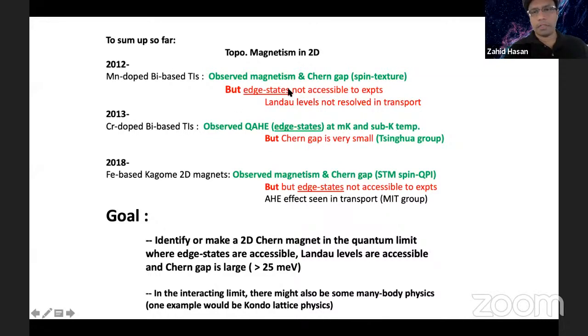In the first material where we observed a Chern gap, this manganese-doped bismuth-based TI, and then in chromium-doped bismuth-based TIs, groups in China, the Xue group, found this quantum anomalous Hall effect, but it's at very low temperature, tens of millikelvin. The gap is small and you cannot really do spectroscopy or a detailed study of this state or what type of magnetism has been realized there. You just do transport, you see quantization, and that's mostly it.